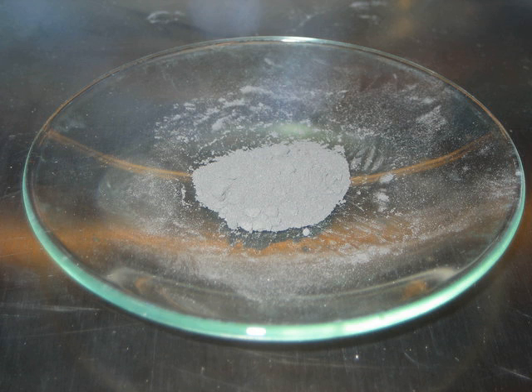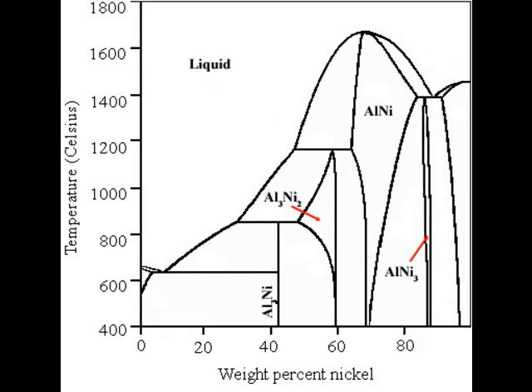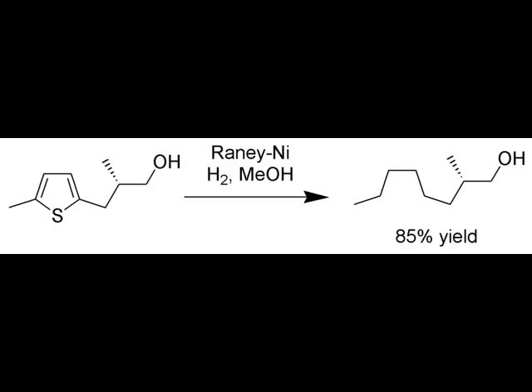The temperature used to leach the alloy has a marked effect on the surface properties of the catalyst. Commonly used temperatures range from 70 to 100 degrees Celsius. The surface area of Raney Nickel and skeletal catalysts in general tends to decrease with increasing leaching temperature. This is due to structural rearrangements within the alloy that may be considered analogous to sintering, where alloy ligaments start adhering to each other at higher temperatures, leading to loss of porous structure. Before storage, the catalyst can be washed with distilled water at ambient temperature to remove remaining traces of sodium aluminate. Oxygen-free water is preferred for storage in order to prevent oxidation of the catalyst, which would accelerate its aging process and result in reduced catalytic activity.